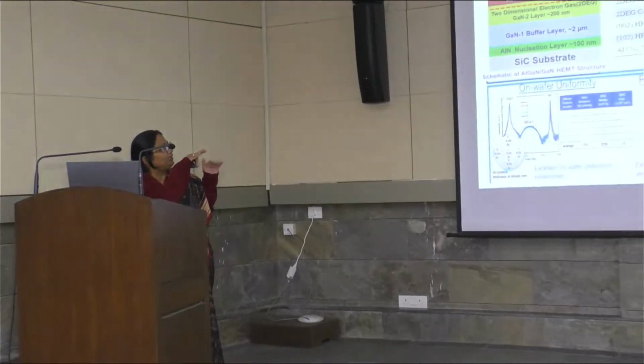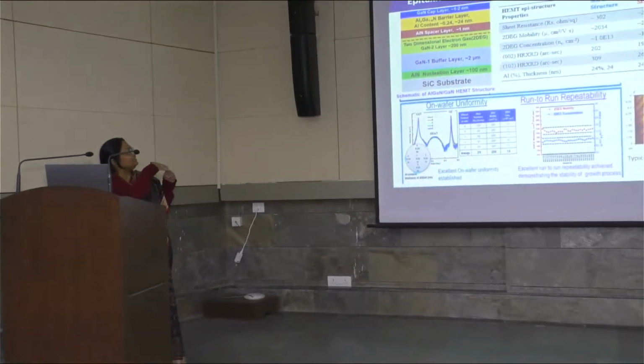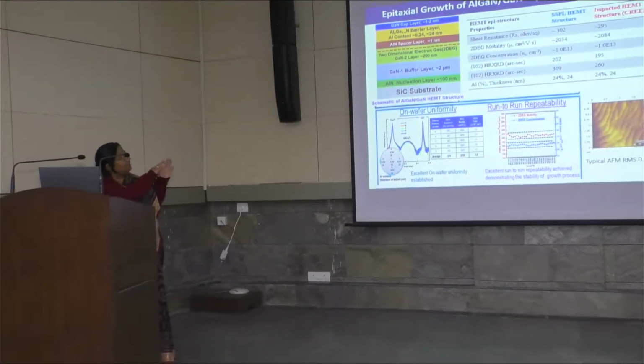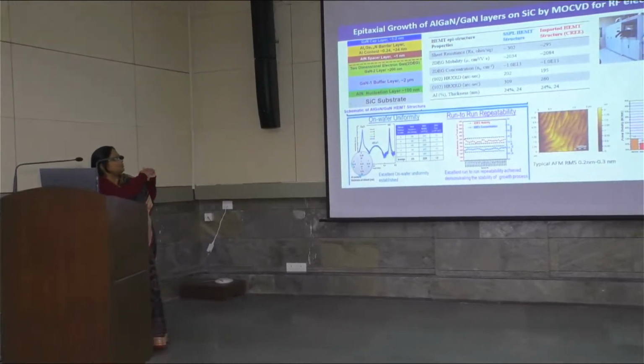And all this is done using what is called MOCVD. I don't know if you've heard of it. It's metal organic chemical vapor deposition. And the challenge here is that each of these layers has to be grown at a different temperature. And you have to have very atomically sharp interfaces also. So these are the challenges. This material growth process has to be optimized.